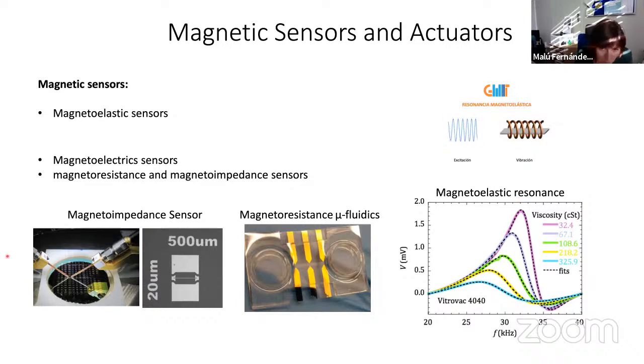Here you can see one magnetoimpedance sensor and the size of these devices that we can prepare. And this is a magnetoresistance sensor that is combined with microfluidics. In this case, we are preparing this kind of device to see if we are able to detect when the bacteria swim along the microfluidic channel, and if we are able to quantify with the magnetoresistance sensors the amount of bacteria in the channel.